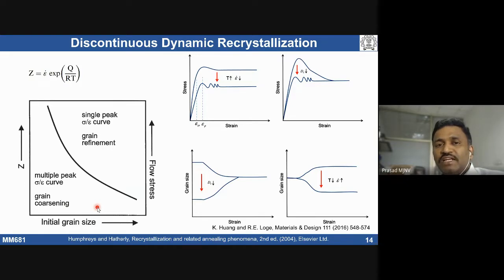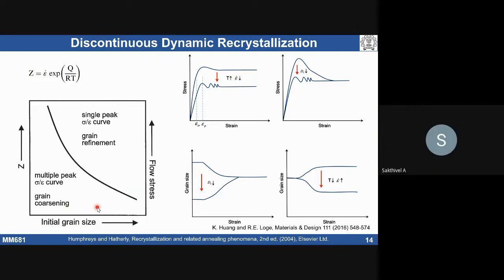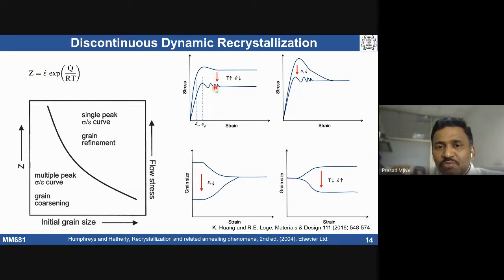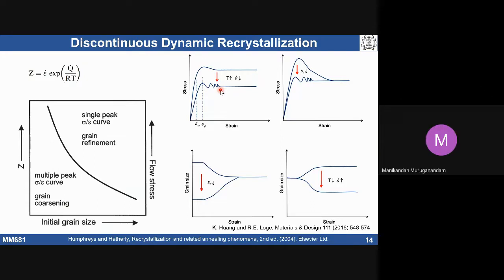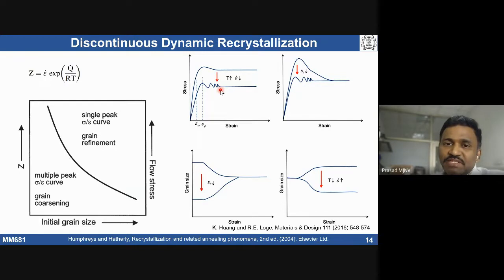Any doubts here? Is it clear? Yes, sir. So why are you getting multiple peaks? What does it represent? Because the test was showing multiple peaks. Sir, multiple recrystallization cycles occur. Yes, the cycles. Initially the material is going to get completely recrystallized by the end of this. Again we see hardening, again recrystallization, again hardening and recrystallization. These are multiple recrystallizations. That means in this case the microstructure is partly recrystallized. After a certain amount of deformation, full recrystallization happens.